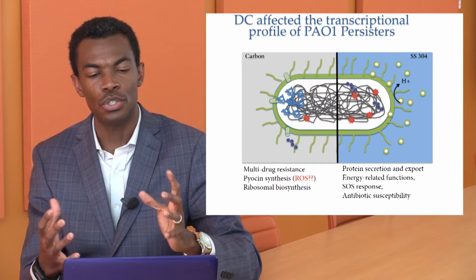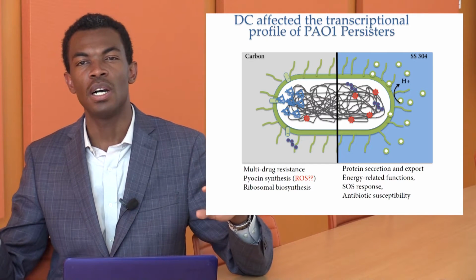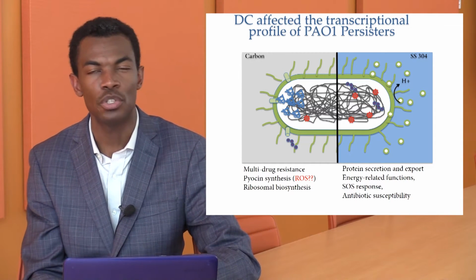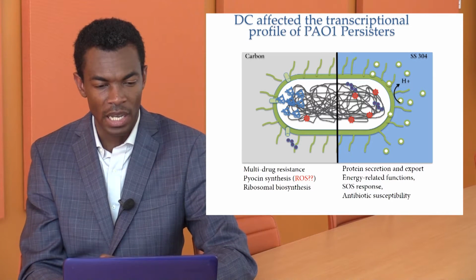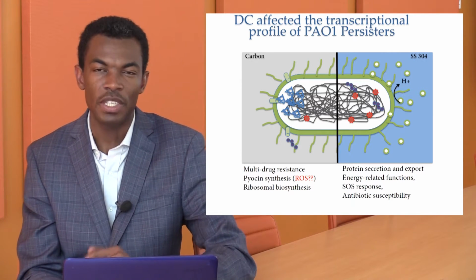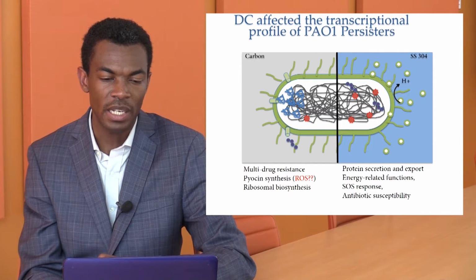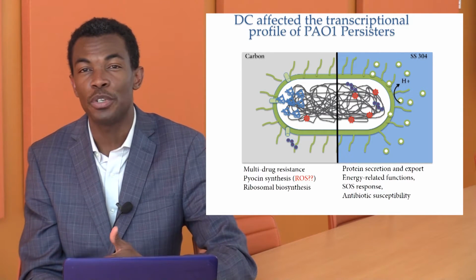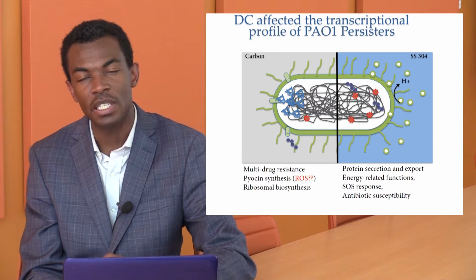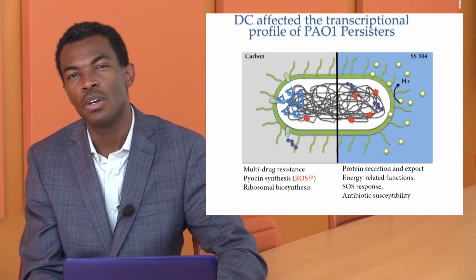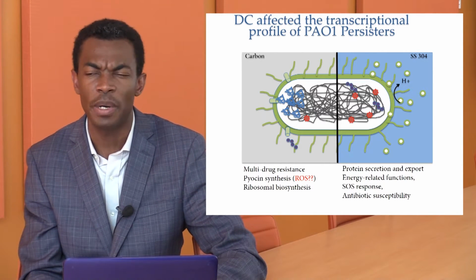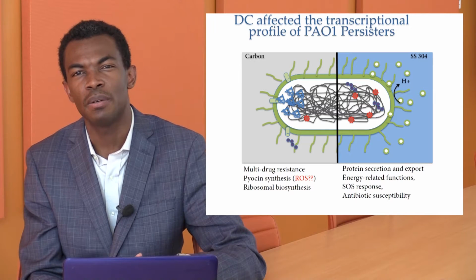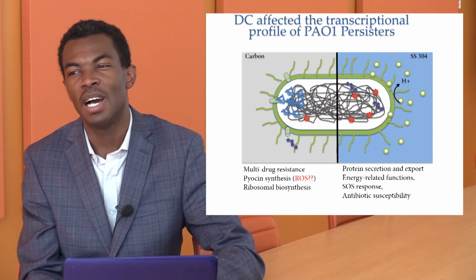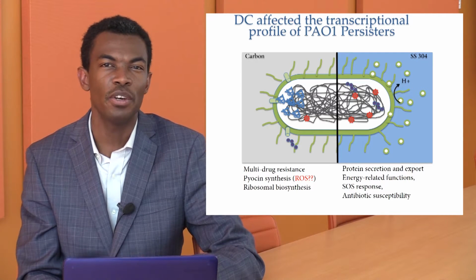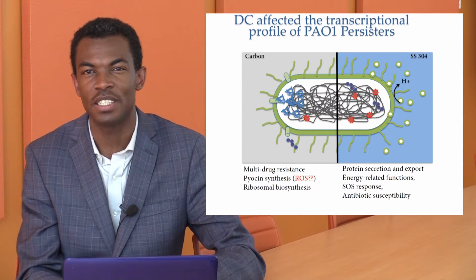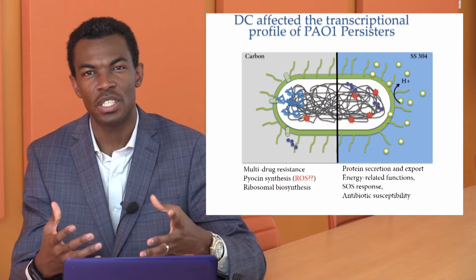So here in these slides, what I tend to show is the difference between the expression of the transcriptional profile of the cells treated with carbon electrode or stainless steel electrode. In the carbon electrode treatment, we can see that the cells start producing a lot of proteins, and among the most of the proteins that were secreted by the cells were the so-called pyocin proteins. The pyocins are just like phages that the cells can even produce themselves as a means of committing some type of suicide, if we can say so. So they're mostly phages that can lyse the cells.